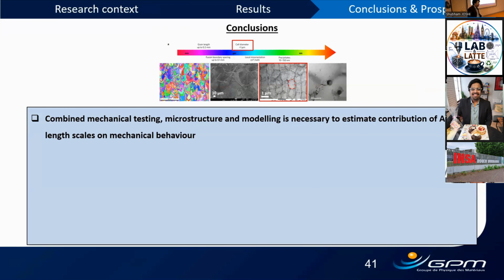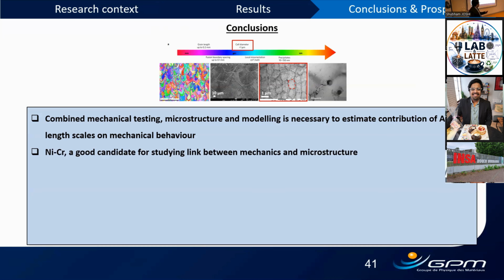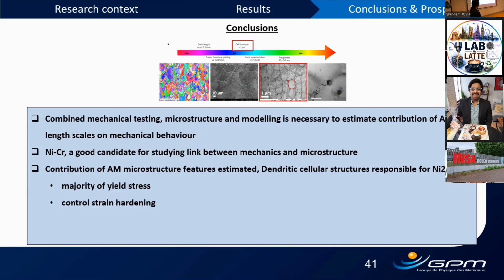So just as a bird's-eye view to conclude, in bullet points: combined mechanical testing, microstructural characterization, and modeling is necessary to estimate the contribution of AM length scales on mechanical behavior, at least for nickel 20 chromium. Nickel 20 chromium, or in general nickel chromium, seems to be a good candidate to study this link because, as I said, it can easily avoid complexities like dislocation annihilation. Clearly, we could conclude that dendritic cellular structures, after the contribution of AM microstructure, are responsible for the majority of yield stress and control strain hardening.